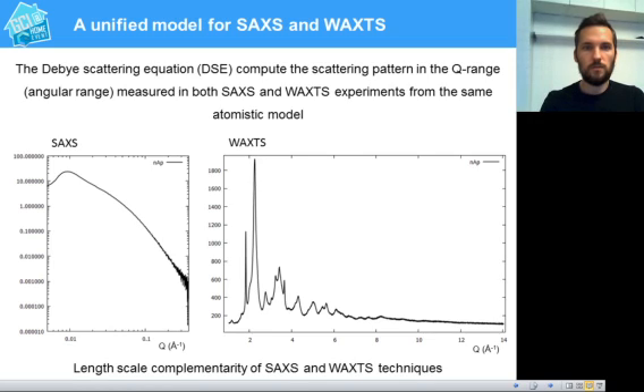To integrate this information in the wide angle, we used a unified model for SAXS and WAXTS analysis based on the Debye scattering equation, which can compute the scattering pattern in the Q range measured by both the techniques, starting from the same atomistic model. And this approach will benefit from the length scale complementarity of the two techniques.